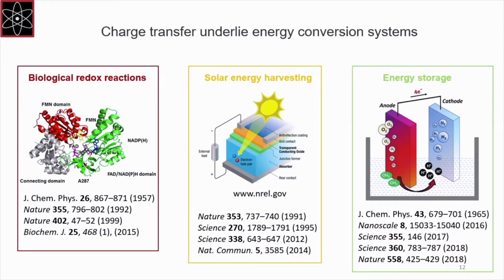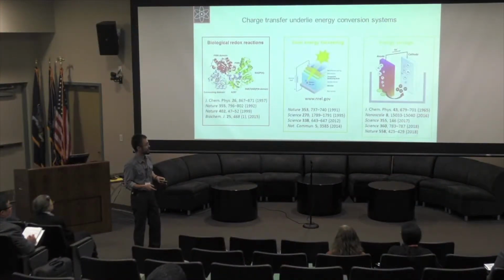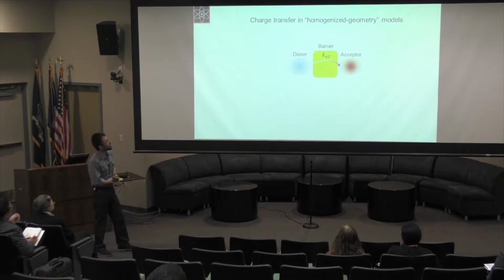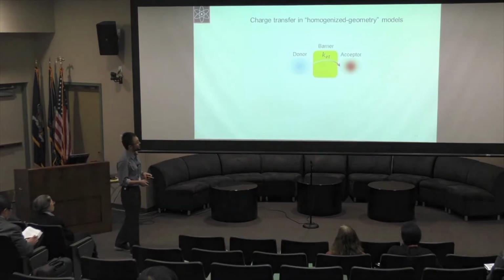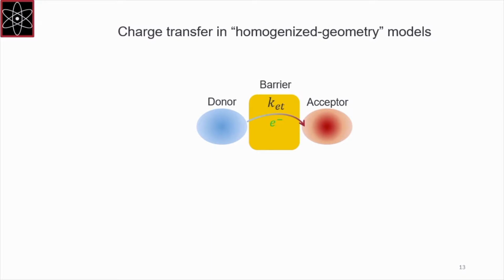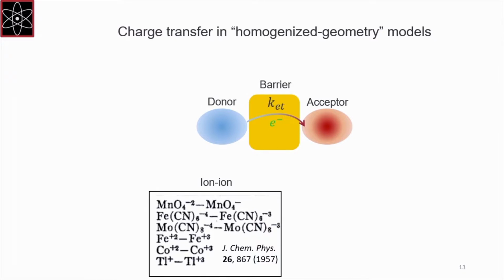And in all of these processes, the movement of electrons across interfaces between molecules, between electrodes and chemicals are very important, and it's an omnipresent phenomenon. So the basic mechanism of this process has been studied for more than half a century, using many model systems. But so far, most of the model systems have what I would consider a homogenized geometry, meaning that the effective distance between the donor and acceptor is pretty much averaged over from an ensemble point of view, either through just rapid motion, mostly through rapid motion, as in the case of solution phase reaction between ions.